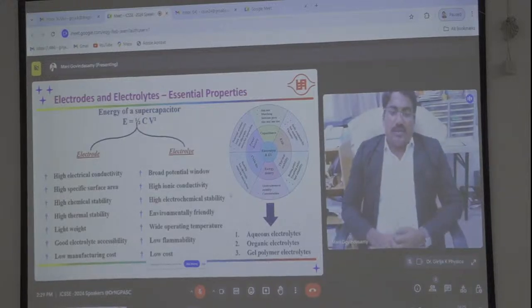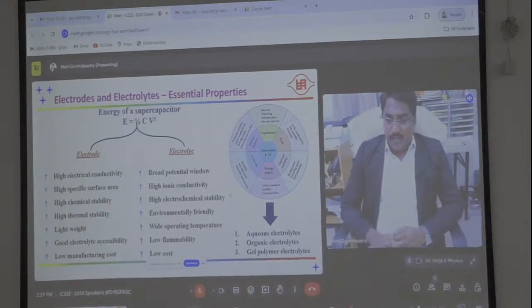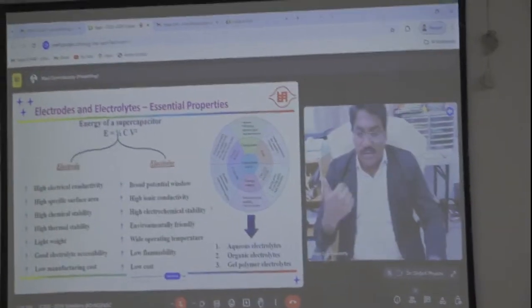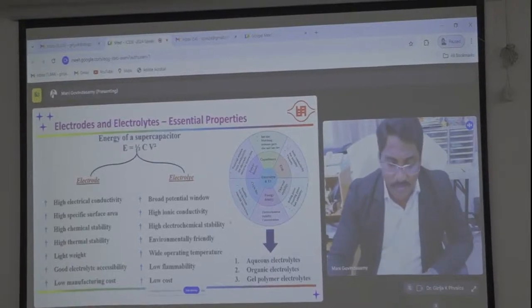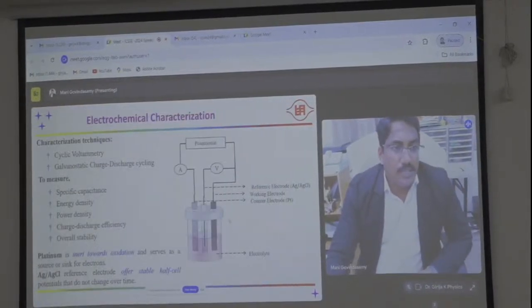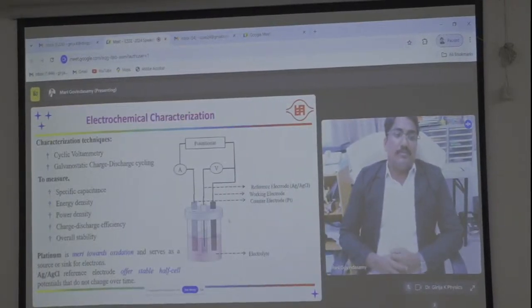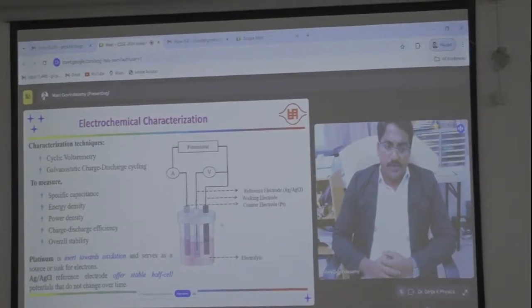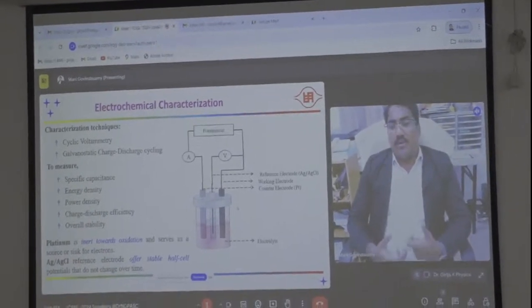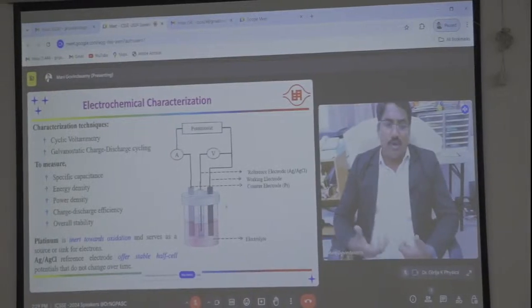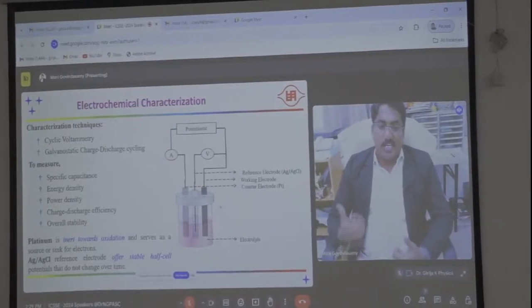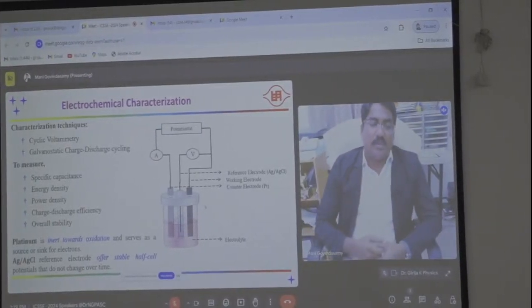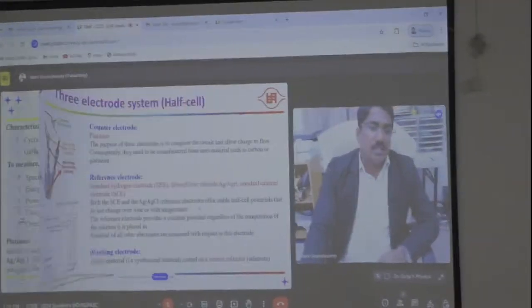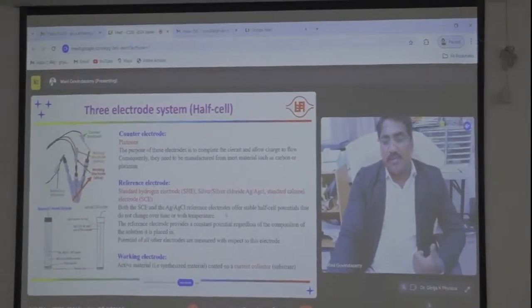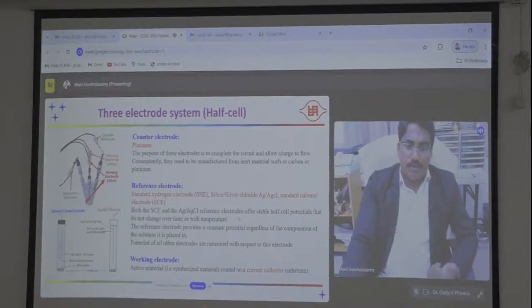So usually we are developing aqueous electrolyte, and then organic electrolyte also we are using, and gel, for example, solid related and gel polymer we are using for electrolyte as concept. So basically for 3 electrode system we are using Pt and silver chloride, and for example working electrode as a nickel foam or carbon cloth or stainless steel mesh. So these are the substrates we are developing for 3 electrode system aspects. But when we are moving to 2 electrode system, we are using coin cell and we are developing pouch cell.